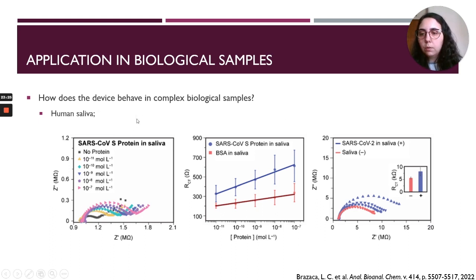for diagnostics. So what we did here is we used human saliva for building the calibration curves. So right here you can see the EIS spectra. As previously, we do have an increase in RCT with increased concentrations of S protein, but we can also see that BSA and S protein curves are quite close right now. This is probably due to the presence of non-specific interactions because there are a lot of other molecules in the saliva. But we can still differentiate between the two species. We also did add some inactivated SARS-CoV-2 viruses to the saliva, and we were able to differentiate between negative and positive samples, showing that this could be an alternative method for diagnostics.